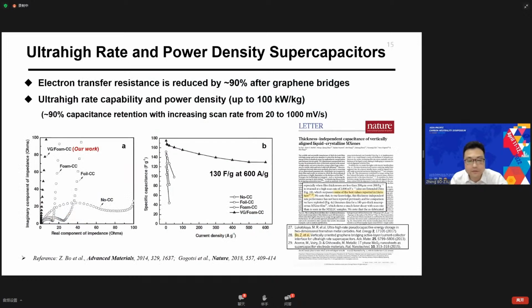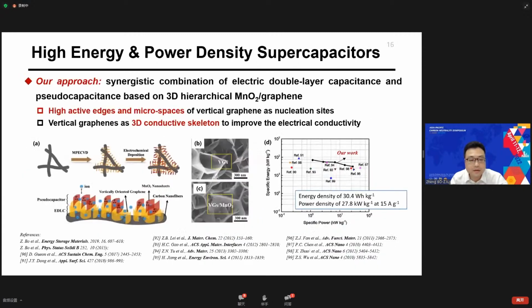Based on the above work, a series of high-performance supercapacitors are developed. Using vertical graphene bridges, the electron transfer resistance is substantially reduced, demonstrating supercapacitors with ultra-high rate capability and power density. A proper combination of electric double-layer capacitance and pseudo-capacitance shows great potential to realize both high energy and high power density.